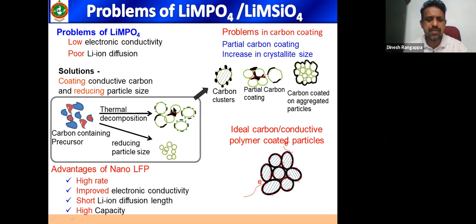But most often the problem in carbon coating was carbon clusters or partial carbon coating or carbon coating on agglomerated particles. All this leads to poor electrode performance. But with the development and progress in synthesis technology, we can improve the carbon coating on the electrode particles. So ideally, if we can achieve this kind of carbon coating, then we would get high capacity, high rate, and improved electronic conductivity, short lithium ion diffusion, and other advantages.